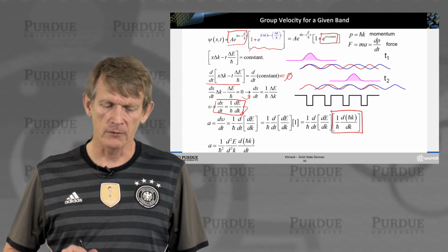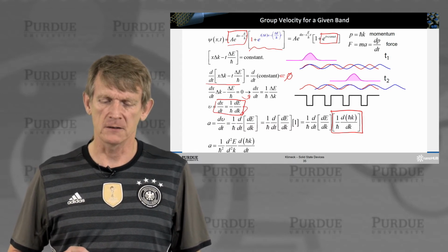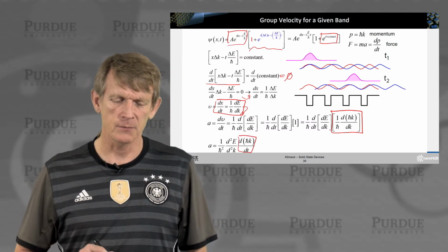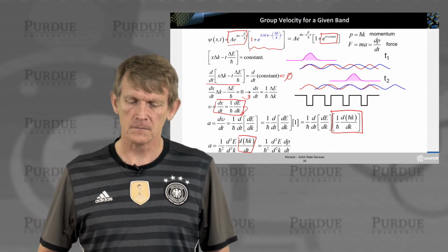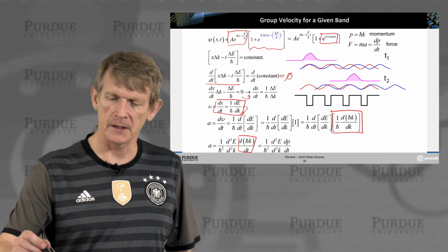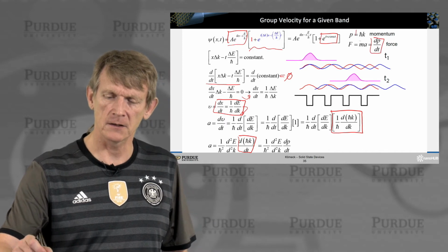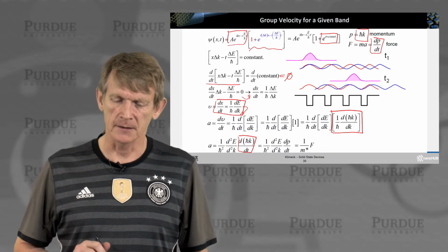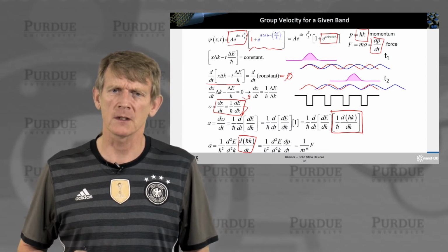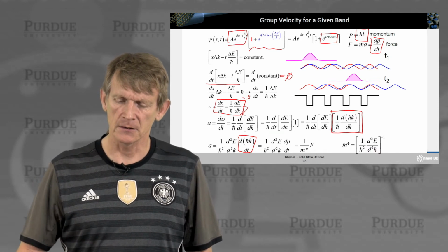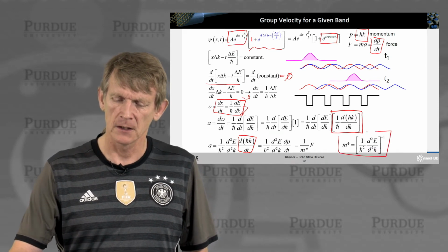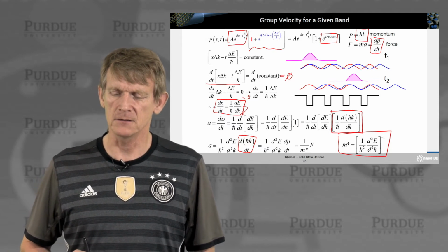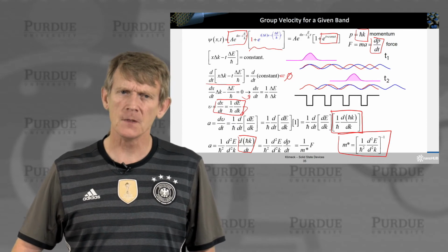Now, you can rearrange this term and rearrange the differentials where you end up on the far right with d(h bar k)/dt. And that you can identify again over here with this expression from up here. That is the differential of the momentum. And the differential of the momentum is 1 over m star times F. So you can define something conceptual as m star as being 1 over h bar squared d2E/dk squared.